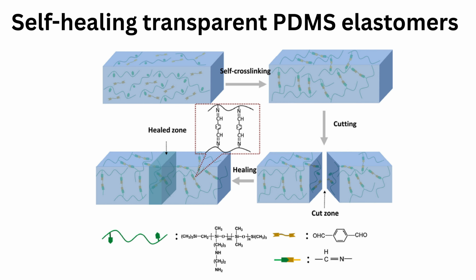raw materials. The formation of imine bonds was demonstrated by infrared spectroscopy and Raman spectroscopy, and the reversible imine bonds could promote the self-healing of fracture surfaces without the stimulation of external conditions. The healing rate of the elastomer was found to be 42.6% after 5 minutes and 97% after 1 hour. The elastomer also demonstrated excellent recyclability and processability.